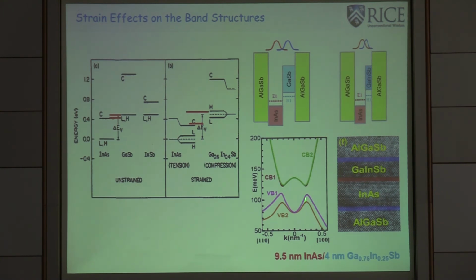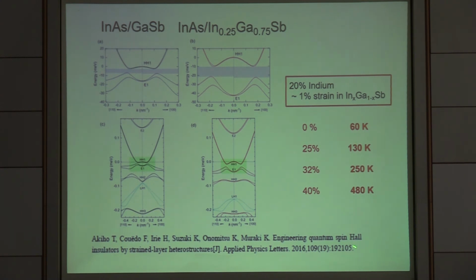So the calculation shows indeed one can get this kind of effect in real samples. Of course, this technique is widely used in industry for making superlattice infrared detectors. So we just borrow this technique for the case of the quantum spin Hall effect. This is a calculation done by another group in Japan. So for 20% indium, you induce about 1% strain in the whole layer. And then if you calculate with the 8-band model, you find the energy gap is going to dramatically enhance if you go to about 2% strain. The energy gap is going to be about 480 Kelvin. So that's much bigger than the previous one.